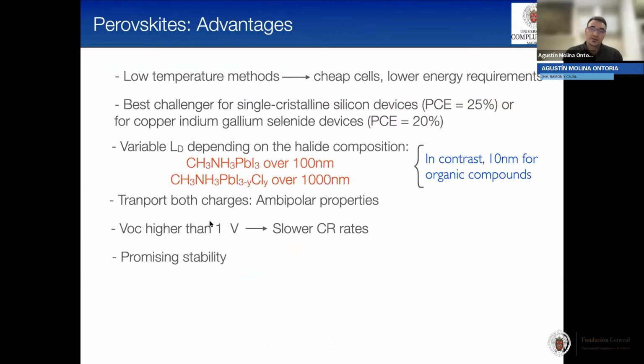Well, among the advantages, I already commented on that. Perovskite can be processed by low temperature methods. That means that we will have very cheap cells with low energy requirements. Probably one of the best challengers, if not the challenger, is to complement silicon. They show variable diffusion length of the exciton depending on the composition. So we can have 100 nanometers in methylammonium lead iodide, and if we dope with a certain amount of chlorine, we can have up to 1 micron diffusion length, in contrast with the 10 nanometers of organic compounds.